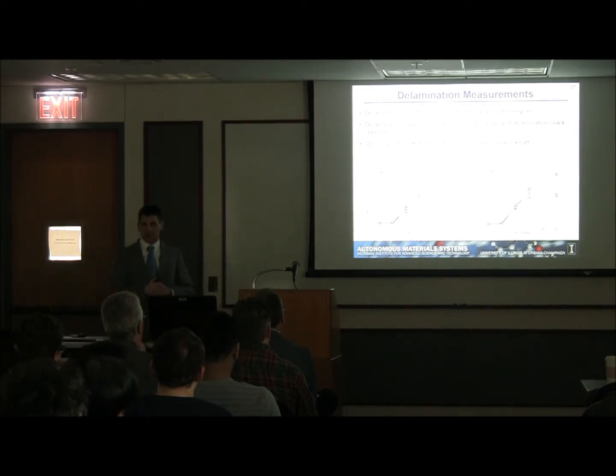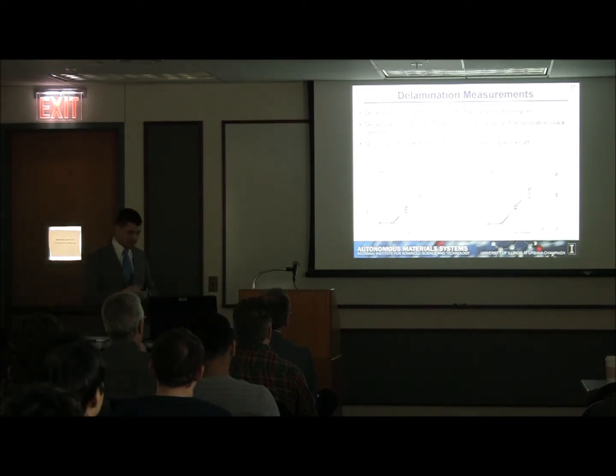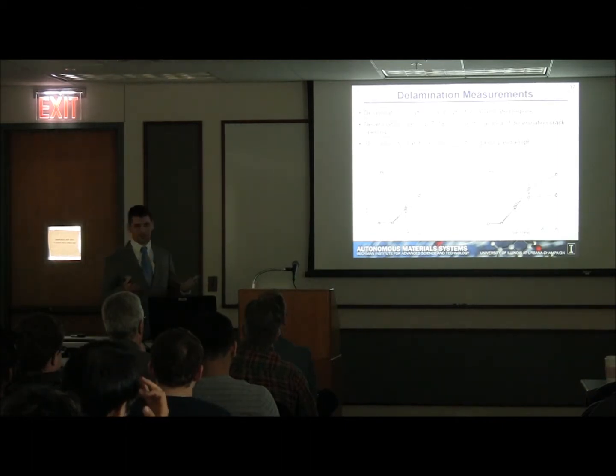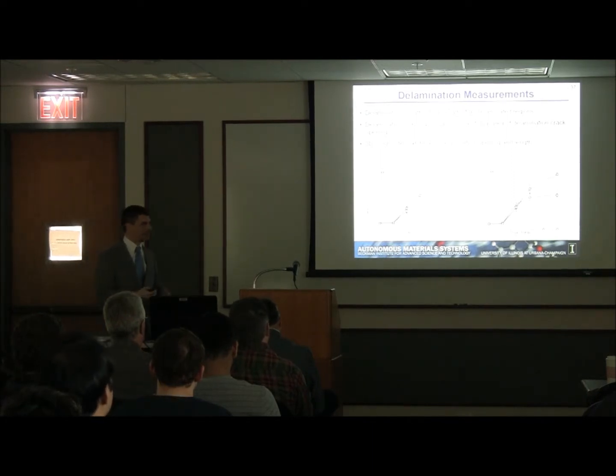So if we plot these delamination metrics as a function of impact energy, we see that as we increase the impact energy, the delamination size grows for both the length and the opening, which is rather intuitive. The more energy you deliver, the more damage you're going to have.